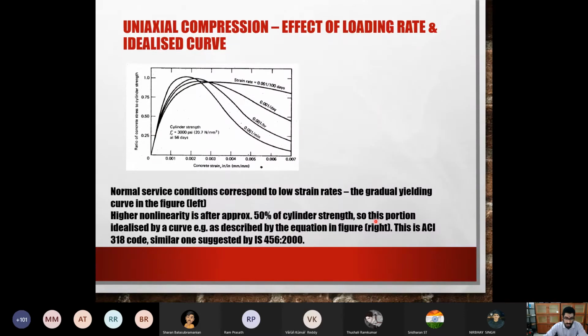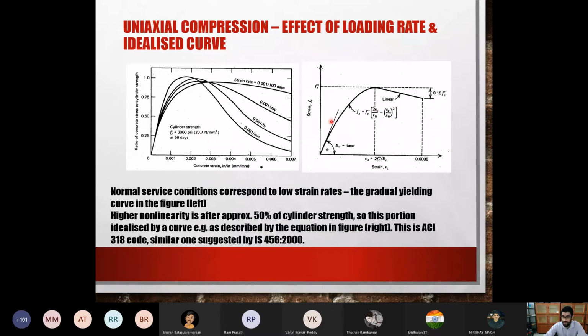This portion of the curve should be idealized by a curve as described in the equation given here. Until about this point, it can be taken as an almost linear thing. Beyond this part, it becomes a bit parabolic, so you need an equation for that. This is the commonly known equation, given as fc equals fc double dash. epsilon c is the current point strain. Epsilon naught is that 0.002 you see over here, and fc double dash is the top peak strength of concrete, the ultimate strength of concrete. Based on that, we'll be able to model this parabola.